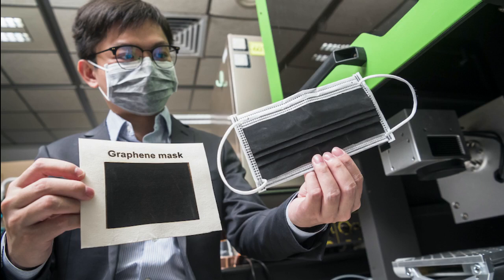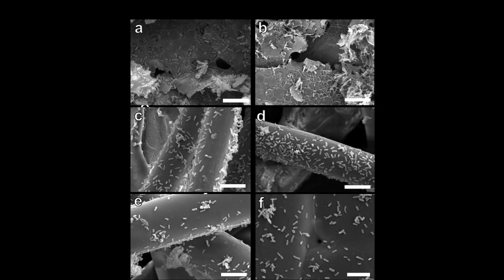The research team tested their laser-induced graphene with E. coli, and it achieved high antibacterial efficiency of about 82%. In comparison,